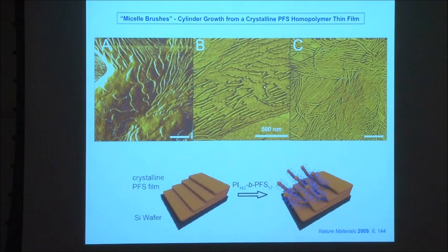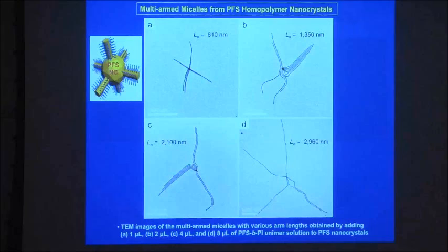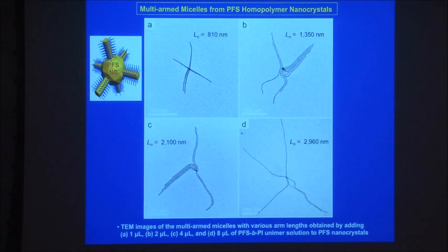So this is using a film. You can also use, instead of a homopolymer film, nanocrystals of the homopolymer. If you take the homopolymer and dissolve it in THF and then squirt it into hexanes, it slowly precipitates. And in the early stages, you generate very, very small crystals of the homopolymer. And if you then add the block copolymer, you grow cylinders from the nanocrystals, and you can see them growing here. As you add more block copolymer, they grow longer and longer, and you can make these star-like structures. So you can really make a lot of different structures using this approach.